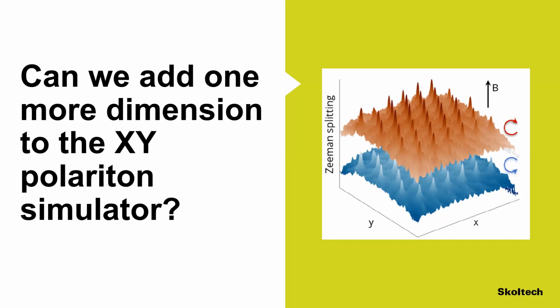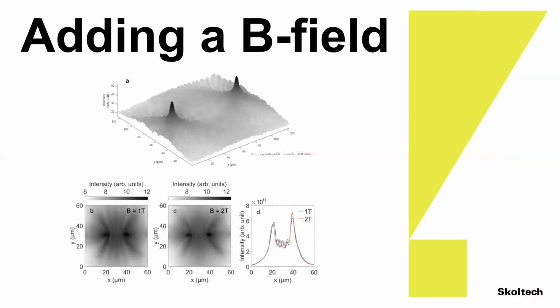So what we have done, we have now utilized the fact that we are dealing with a spinor condensate in a semiconductor. And when I apply an external magnetic field, I split the spin up and spin down components of the polariton condensate, which are coupled through Josephson coupling, and that gives me the 3rd degree of freedom. So we worked with polariton condensates coupled in magnetic fields, and we could see that here, if you look at the parity, by controlling the magnetic field, we can control the coupling. And we scaled this up to lattices and showed that actually the phase arrangement is now minimizing the XYZ.